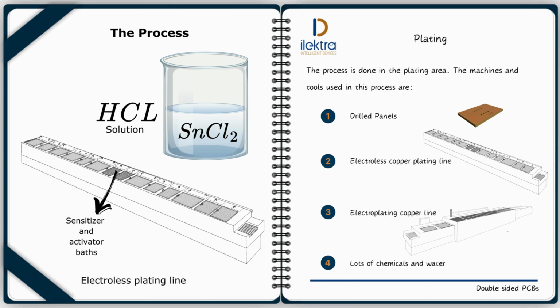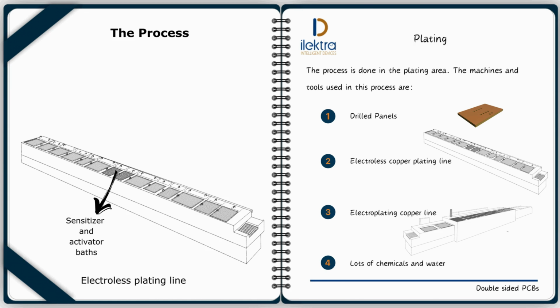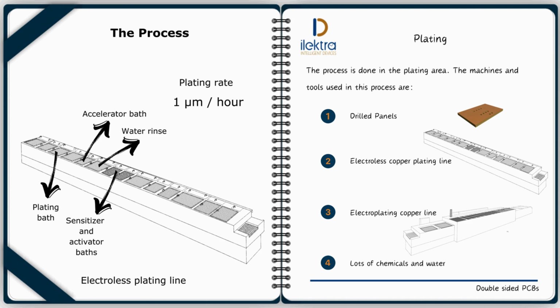Sometimes the panels are first immersed in a sensitizing or pre-activation bath of stannous chloride in hydrochloric acid solution to improve ion absorption. The activation chemical treatment process creates byproducts that will slow down and compromise the plating process. Therefore, the panels are immersed in an alkaline bath to clean them. Now that all surfaces are made catalytic, the panels are immersed in the plating bath. Electroless plating creates a uniform layer of copper on all surfaces, no matter the geometry, but is a slow process. On average, the deposition rate is 1 micrometer per hour. Many things can and do go wrong here. The temperature, pH, reducing agent and copper ion concentrations in the bath need constant monitoring and adjustment.